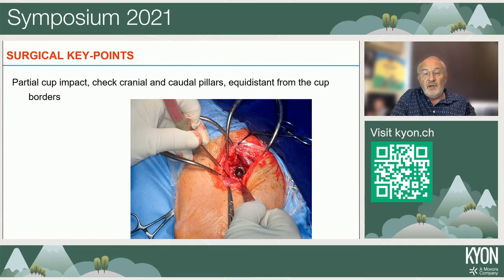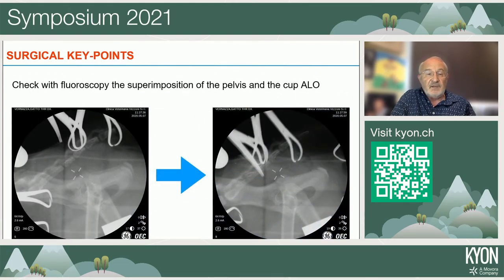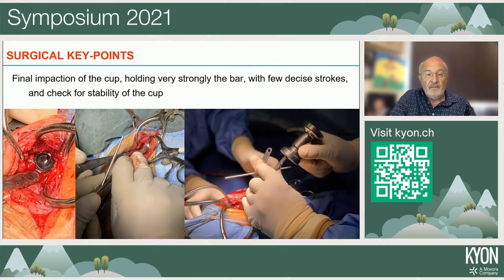As soon as we have a partial impaction, checking that it is well seated according to the cranial and caudal pillar, so it's well centered inside the acetabulum, we need to take a fluoro, because we could have moved the dog or the cat during surgery. As you can see in this case, the pelvis was a little bit oblique. So we set the pelvis in a proper view, just tilting the table or moving the dog, and then we can check the ring of the cup to be sure that we achieve the proper angle of lateral opening. And then we can do our final impaction with a few decisive strokes well counteracted by the assistant.